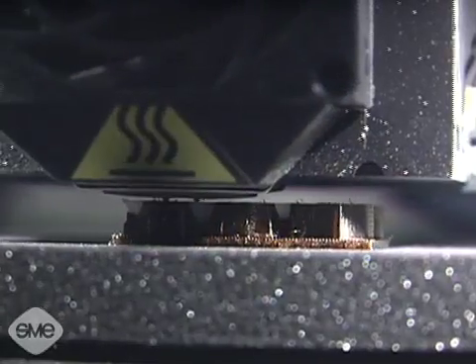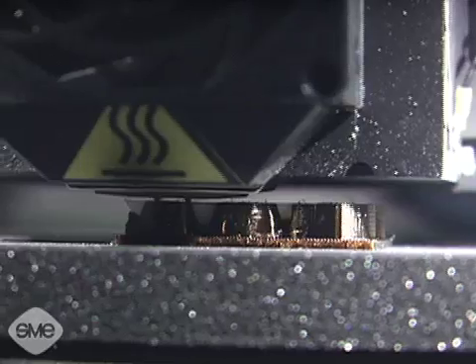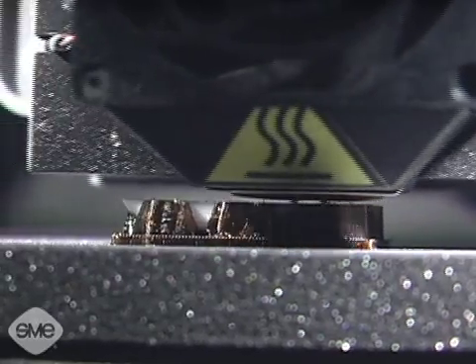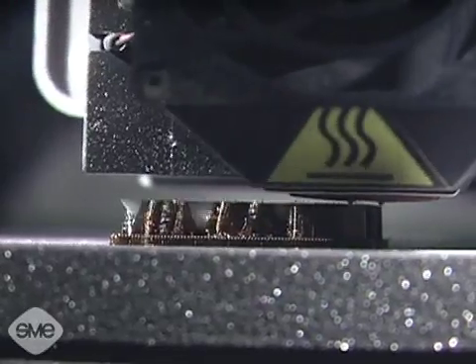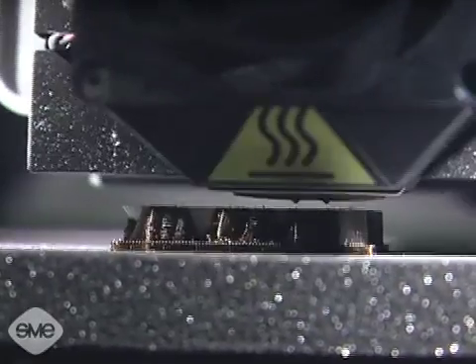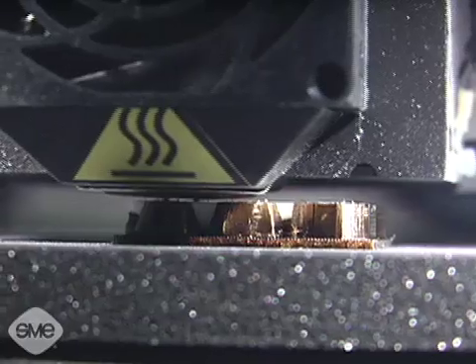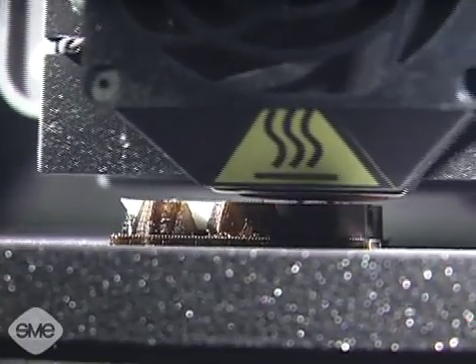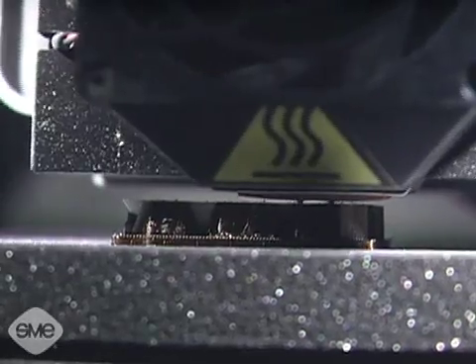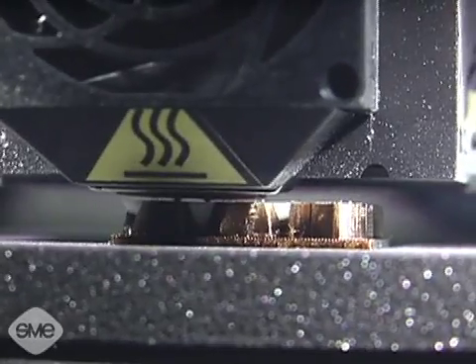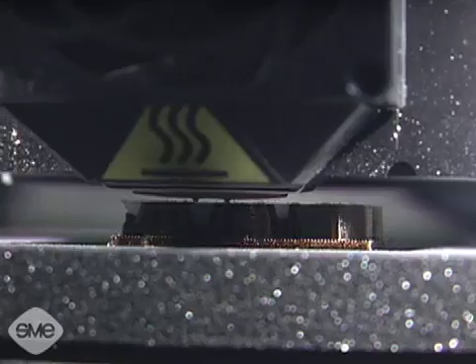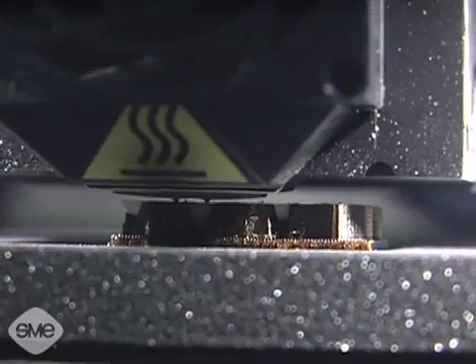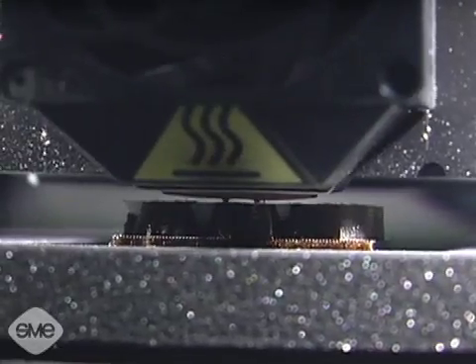The molten thermoplastic is channeled through an extrusion tip, which reduces it to a fine bead for deposition onto a substrate material. After depositing each bead, the tip flattens it in preparation for subsequent layers, and the model is built up layer by layer. Layer thickness is typically between five thousandths of an inch to thirteen thousandths of an inch.